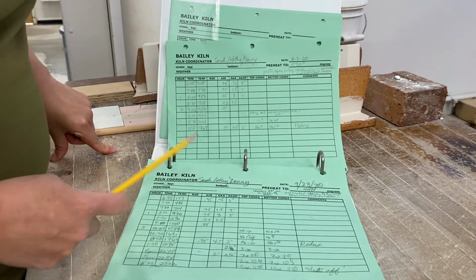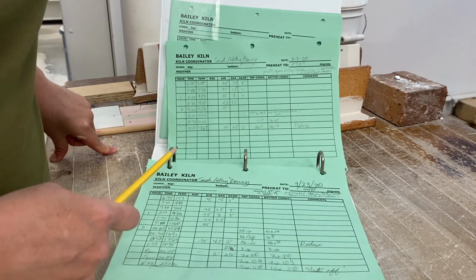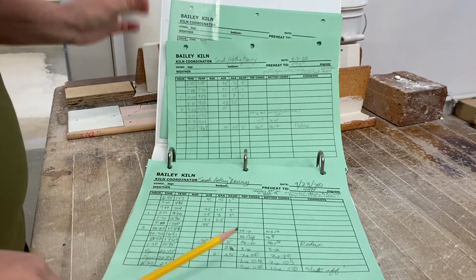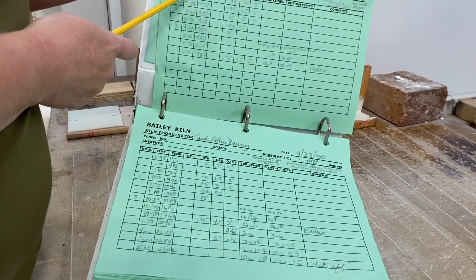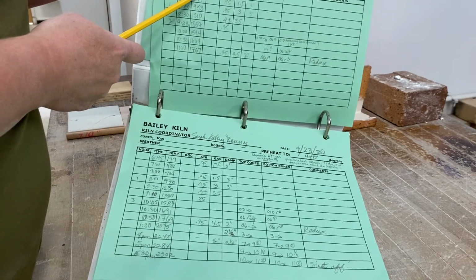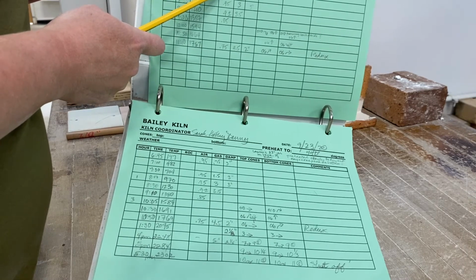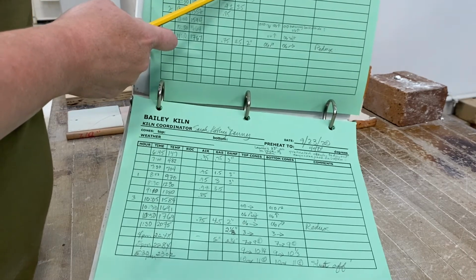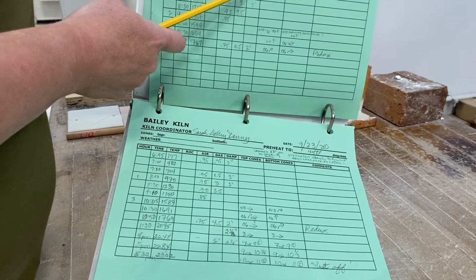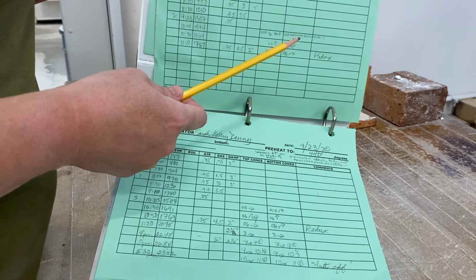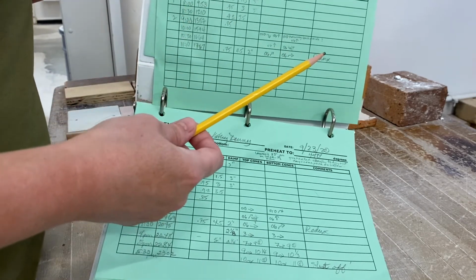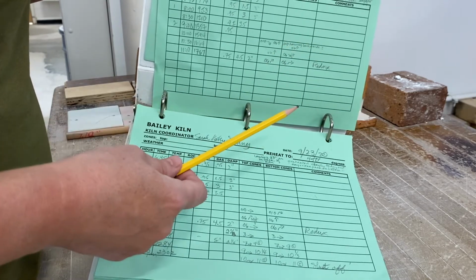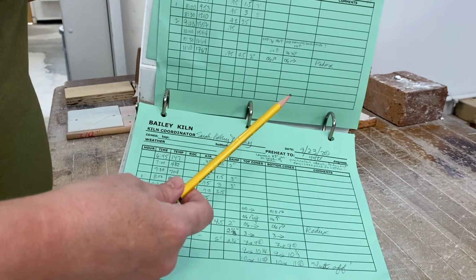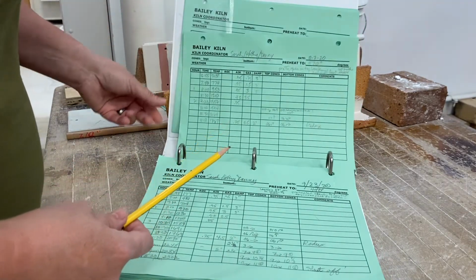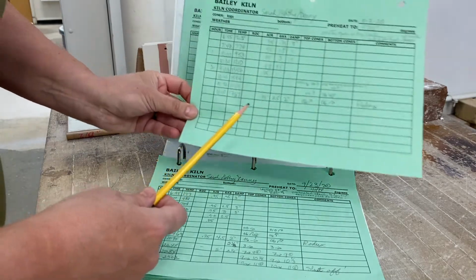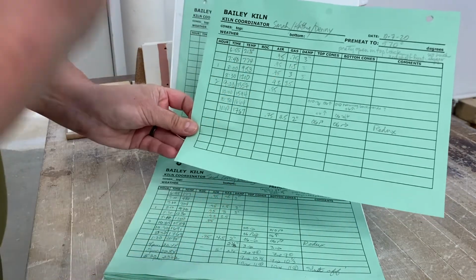This is what we call our kiln log for one of our cone 10 reduction gas firings. And what we have here is a chart where we're noting the time, the temperature from the digital readout inside of the kiln, as well as the air setting, the gas setting, and then our damper. And how open or closed the damper is makes a really big difference in terms of the airflow within the firing. And when we go into reduction, we close that damper to cause less oxygen to be able to flow throughout the kiln.